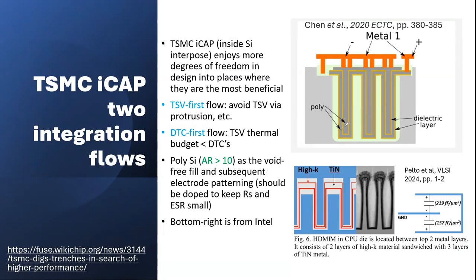This gray part is poly, and this yellow part is the high-K dielectric. It suggests two flows: TSV first, where they put the TSV in first, or DTC first. TSV first because they want to avoid the TSV via protrusion problem. If you do DTC first, then the TSV thermal budget needs to be controlled, because you do TSV later and need to watch out for the thermal budget. Inside the poly, there is a high aspect ratio of 10. This is a dummy silicon gap fill, just like the RMG process, the polysilicon dummy fill. Pretty good, 10 is reasonable. They could do it.